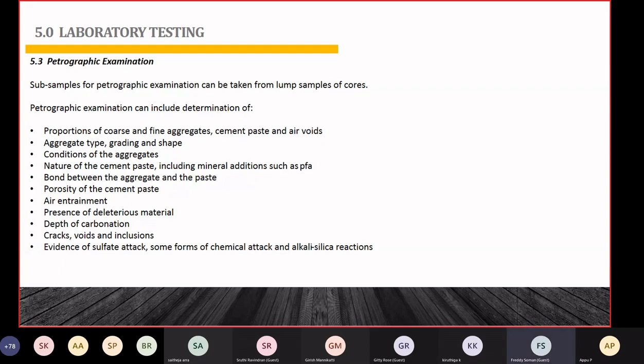Then again, petrographic examination can include determination of proportions of coarse and fine aggregates. Sometimes in arbitration, some doubts come, if somebody suspects or argues about the cement content, whether the cement content is not proper in that particular concrete. One method is the petrographic examination, and another method is the chemical method. The chemical method we can do in the metal lab also. If we take a core, we can find out the cement content.